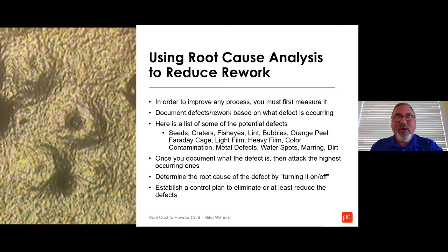So if it's a light spray product and the powder is able to be reclaimed, or excuse me, resprayed, in other words, you're going to get good intercoat adhesion without doing anything to it, you basically pull the part off the line and you put it back on the line, paint it again, as long as you're in that color. Now you've got to add in the cost of doing the color change if you have to go back and do it later. But here's your opportunity now.